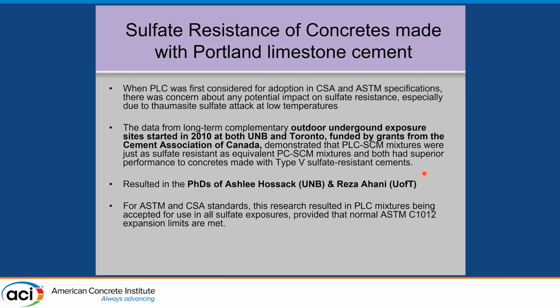So the main concern we said was there's not enough information about sulfate attack. And there was a potential concern about thaumasite sulfate attack, which involves carbonates as well as sulfates at low temperatures and attacks the matrix. And there'd been a case in the UK at the time. Norah Crammond had a conference about thaumasite sulfate attack. And so people were concerned about this whole issue of thaumasite sulfate attack.